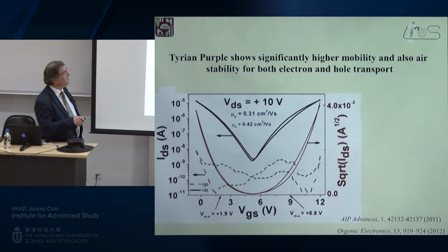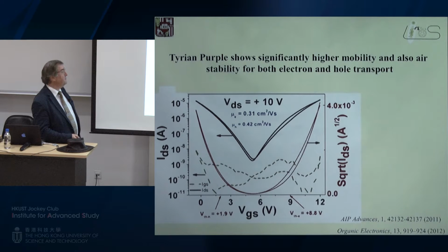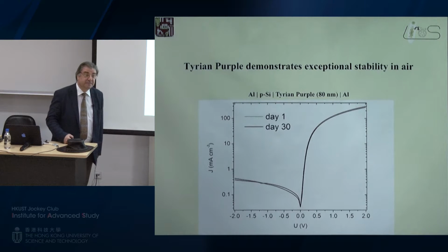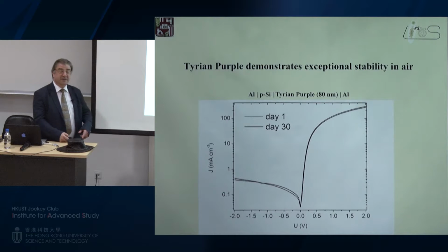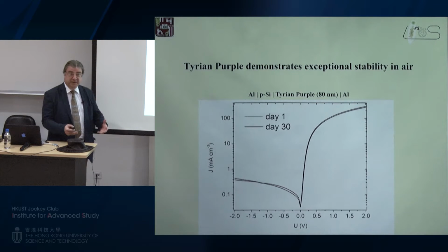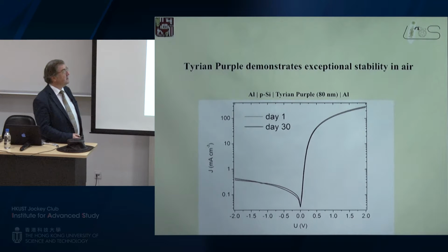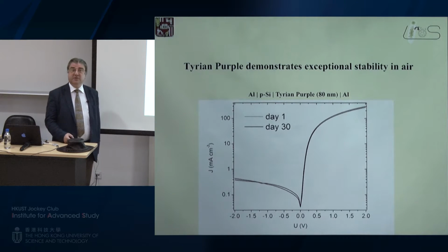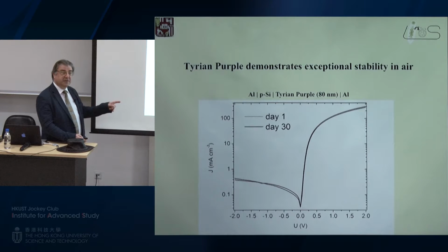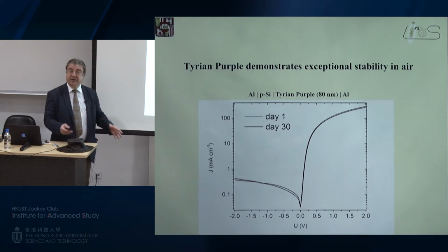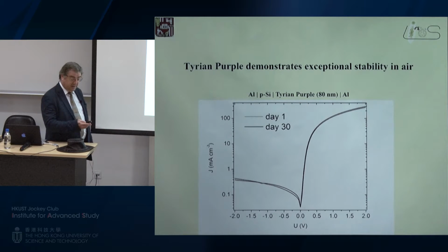So, if you look at this material, it's amazing. I mean, it's perfect ambipolar, more or less negligible hysteresis. You get 0.1 order of magnitude, beautiful mobilities. And this material is stable. And if I say this, I mean it. And we know that organic electronics had always suffered because of the stability issues, especially photostability issues. We have indeed less lifetime, let's say, compared to inorganic silicon with an oxide on it. However, these materials are really stable. You process them in air, you don't need any kind of encapsulation, and they work.